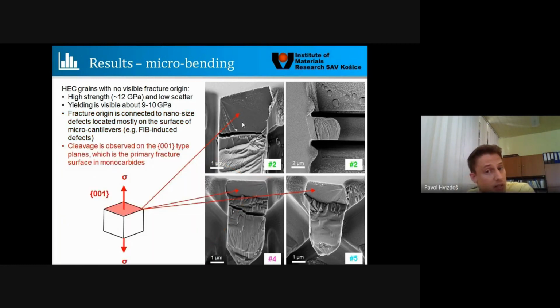The surface we see is quite smooth, and those surfaces are the 001. So the cleavage plane, as we expected, was the 001 plane. Of course, at the bottom part of the cantilevers there is some deviation, but this is simply connected to the change in the deformability once the fracture starts to propagate, because in that case the stress field completely changes. And at the same time, on the top side we always have tensile stresses, while on the bottom side we have compressive stresses, and this causes a different kind of failure.